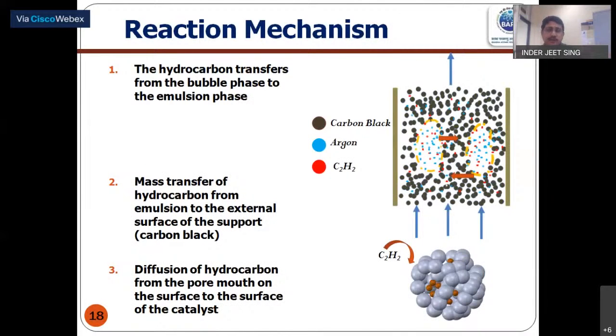But now, after understanding this much, what can we propose about how the process progresses? What happens in a fluidized bed? Typically there are two phases. One is called the emulsion phase, where gas and solids are almost homogeneously mixed, and there is a bubble phase. I am showing two bubbles where mostly excess gases are there. So what happens in the first stage: the hydrocarbon, that is our acetylene, transfers from the bubble phase to the emulsion phase.